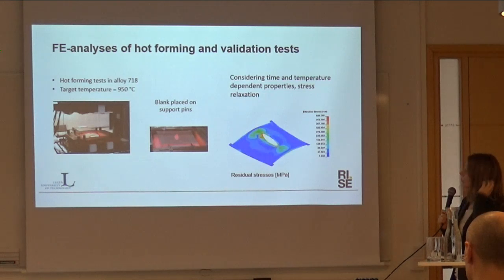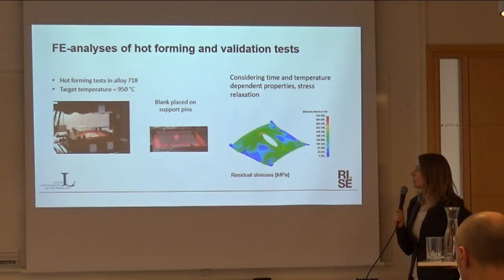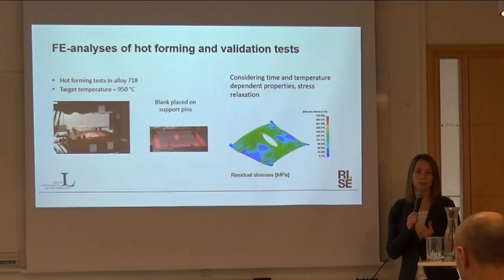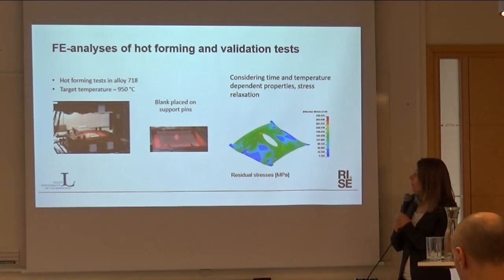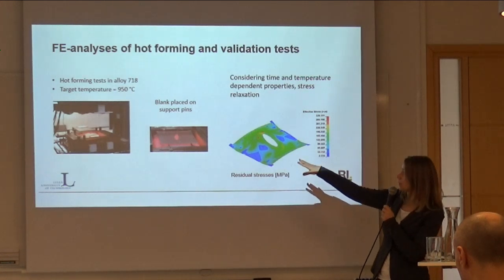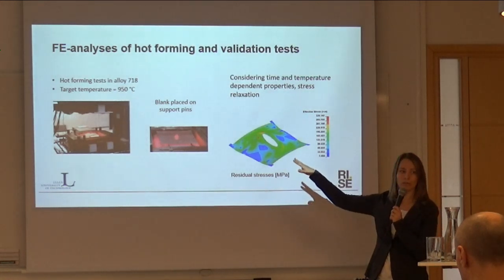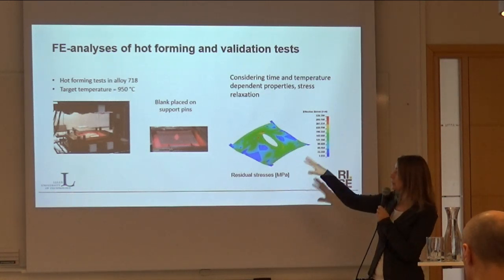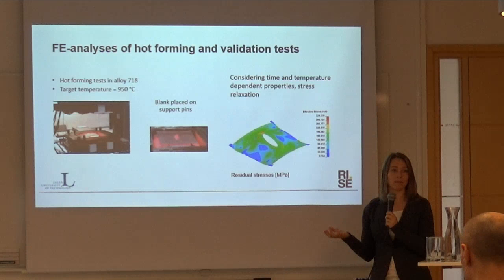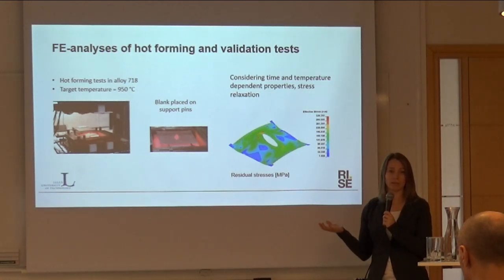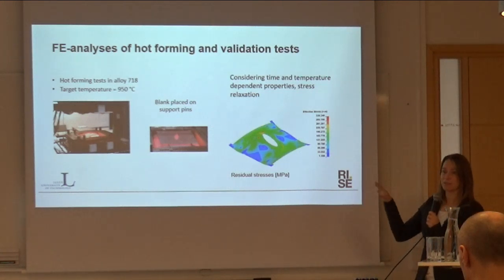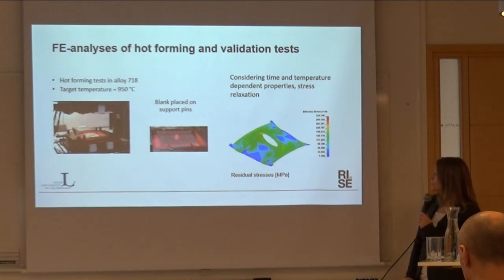Also, we work with hot forming, and this is because the materials are very expensive, so we want to avoid waste. We heat up the material to a target temperature of 950 degrees centigrade. These are very temperature stable materials because the working temperature in the engine is about 650 degrees. So it's very resistant to temperature, and we have to heat them up to a very high temperature.